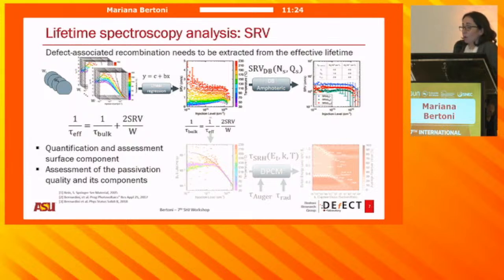All right, so how do we look at surface recombination velocity? How do we do this analysis in a way that is experimental? And the answer is you actually have to create a whole lot of samples. So you create a thickness set with the same wafer quality and basically different thicknesses. You have to coat your system symmetrically. So if you want to look at intrinsic amorphous silicon, you do intrinsic amorphous silicon on both sides. If you want to do a doped layer, you do the same doped layer on both sides. And then, because you know that 1 over tau effective is 1 over tau bulk plus your surface recombination velocity terms, you can actually extract your SRV out of your linear response. So that's a little bit of what we did in this work.